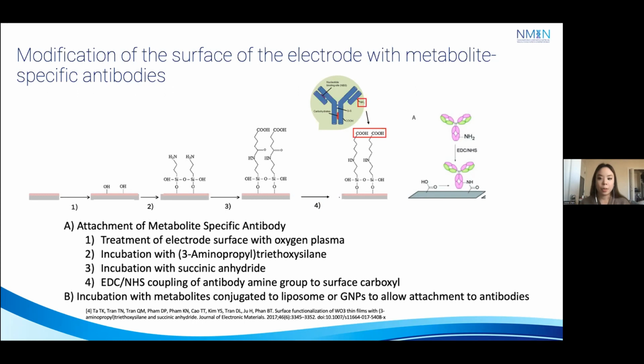And then the exposed carboxyl group of the succinic acid then binds to the amine functionality of the antibody through the amide bond. And EDC and NHS is used in this reaction to increase coupling efficiency and result in a more stable amide bond. And then after the antibody is added, the surface is incubated with the metabolite conjugated to the liposome or the gold nanoparticle to allow attachment to the antibodies.